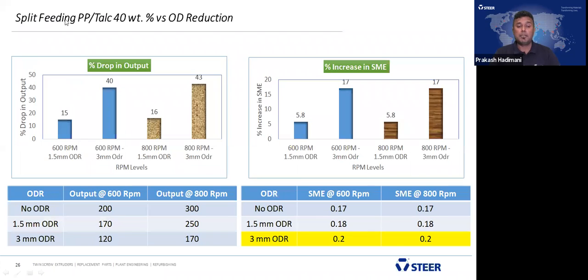If you see, first the split feed method: polypropylene fed from the intake and talc from both the side feeders. With no OD reduction, we observed the throughput for the 40% talc. We observed 200 kg per hour at 600 RPM and 300 kg per hour at 800 RPM. It's a 40 millimeter extruder.